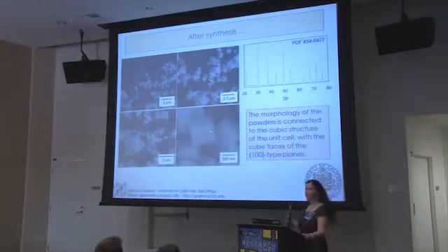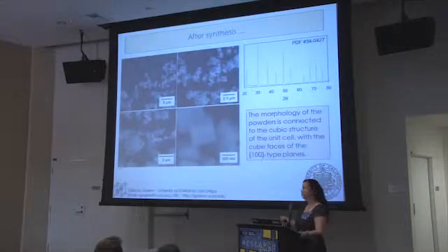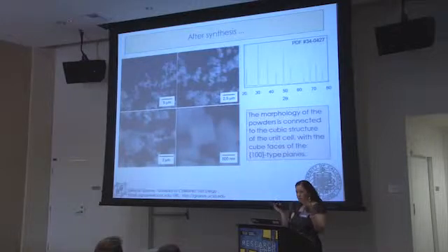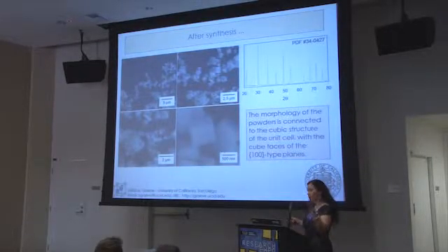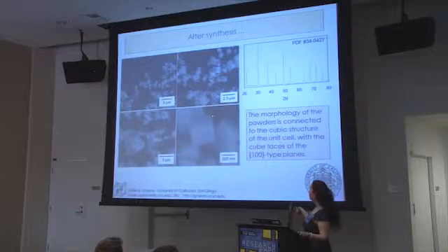This is a mirror of the crystal structure. I showed you that cubic structure, so it wants to have that form. But if it has that sort of unclean oxide surface, you're not going to have that. So with very, very controlled, very clean acid etching of the material, you're going to end up with these very nice nanocubes.